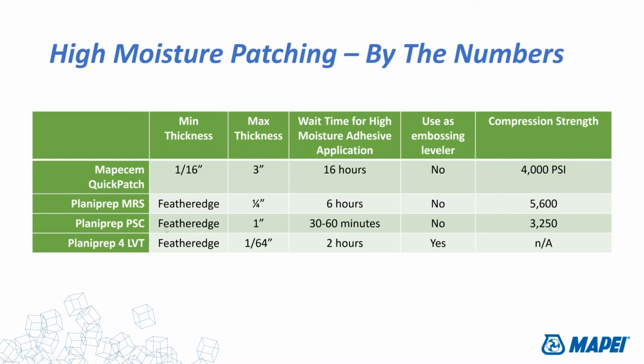Planiprep 4 LVT, as I mentioned before, is a feather edge to a very thin application. It's really a true skim coat and embossing leveler. You're not really going to want to use this in very thick applications, but if you want to skim, that's a great product for it. You can apply adhesives on top of it within 2 hours, and you can use it for an embossing leveler. We don't have compression strength testing on this kind of data, but it really is irrelevant anyway because it's a skim coat, an embossing leveler.